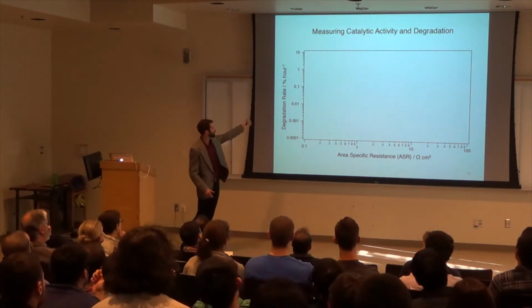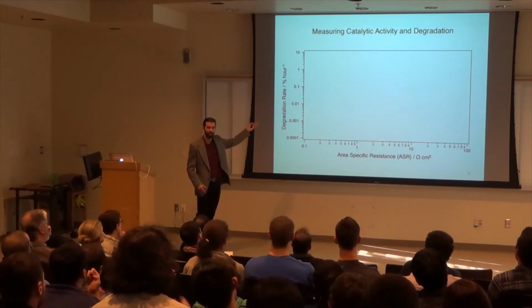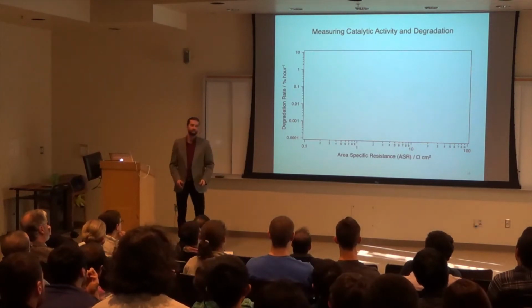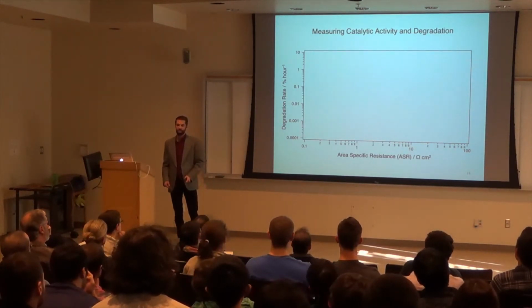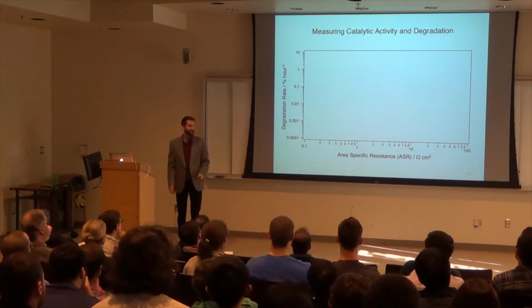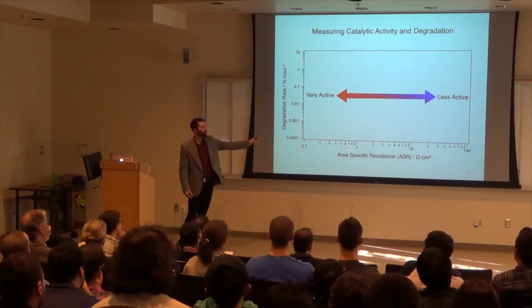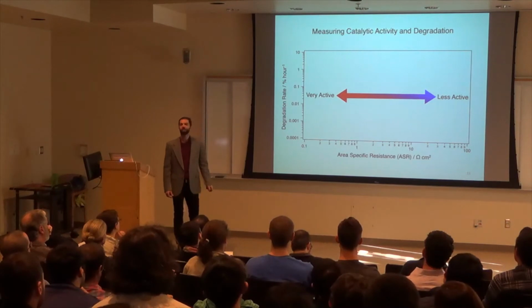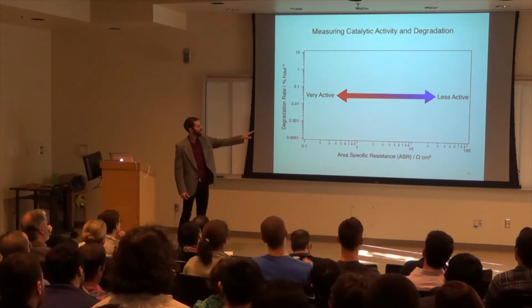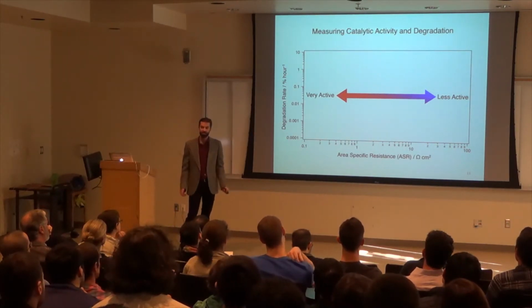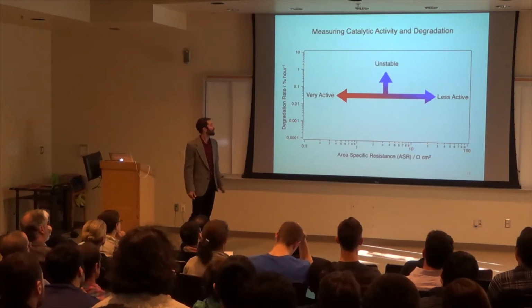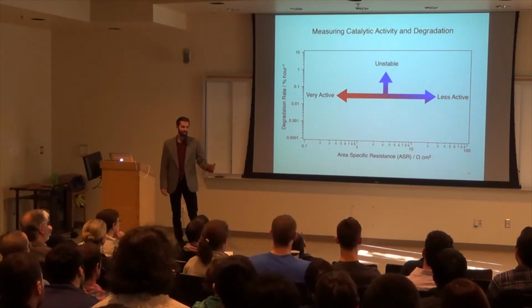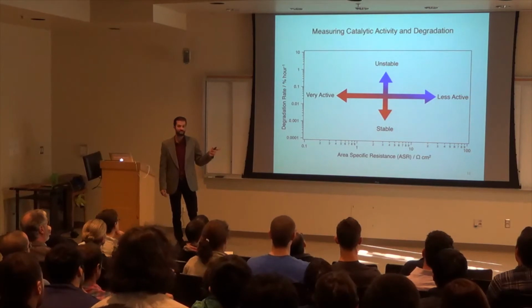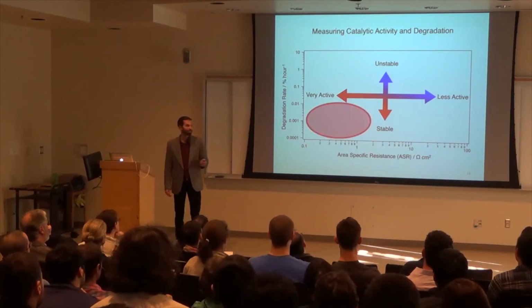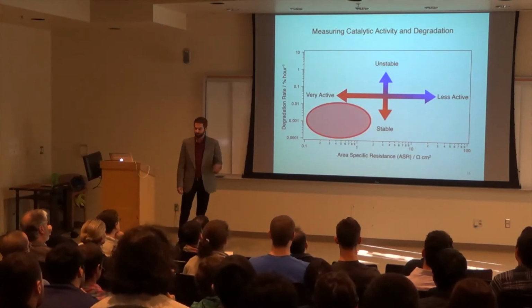On the y-axis, we have the degradation rate as a percentage per hour of how quickly it degrades. And on the x-axis, we have something called area-specific resistance, which tells you how good of a catalyst it is. So with a very low resistance, the catalyst is very active. With a high resistance, it is less active. Similarly, when you have a high degradation rate, it's unstable, and a low degradation rate, it's stable. So our best catalysts are going to be down in this region right here.